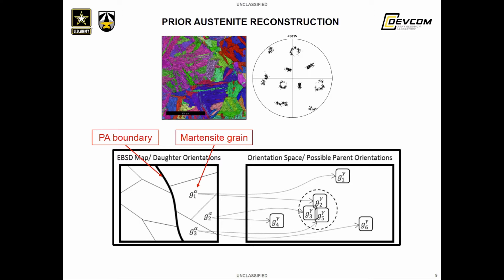So using the inverse orientation relationship, which is kind of depicted in this short formula right here, you can generate all of the possible parents for individual martensite grains and then compare those possible parents to each other. The right part of the schematic is a 2D depiction of the space of orientations. So right now it's showing the possible parents for each of the martensite grains on the left.